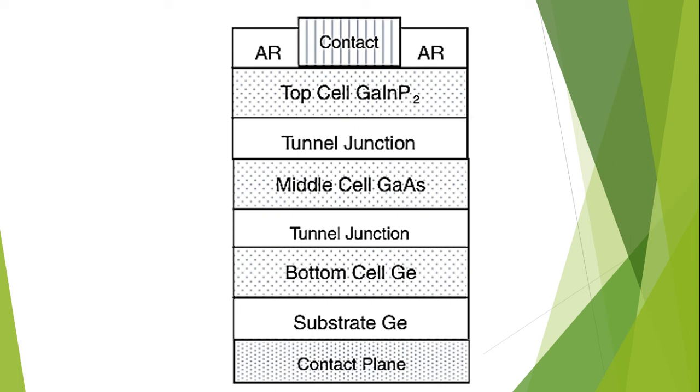Traditional single junction solar cells have a maximum theoretical efficiency of approximately 33.16%, and theoretically an infinite number of junctions would have a limiting efficiency of about 86.8% under highly concentrated sunlight. Currently the best lab examples of traditional crystalline silicon solar cells have efficiency between 20 to 25%, while lab examples of multijunction cells have demonstrated performance efficiency of over 46% under concentrated sunlight.